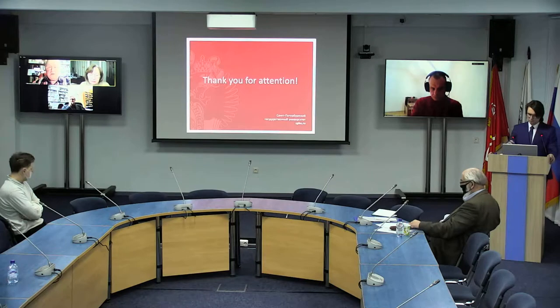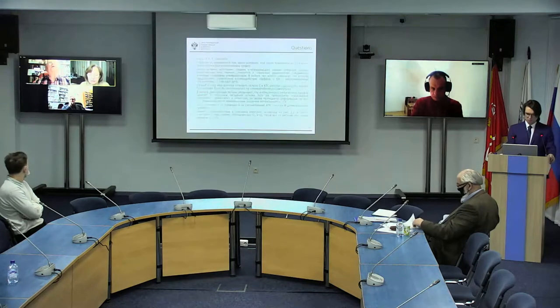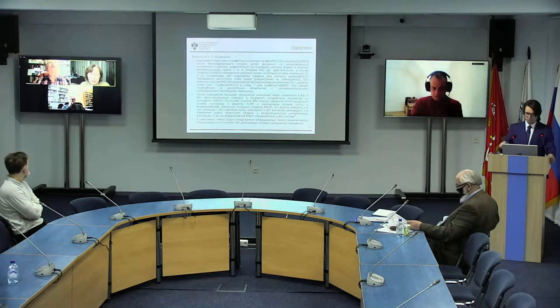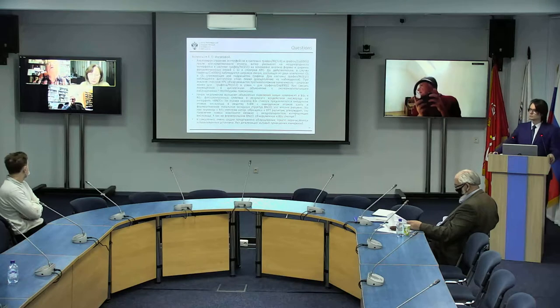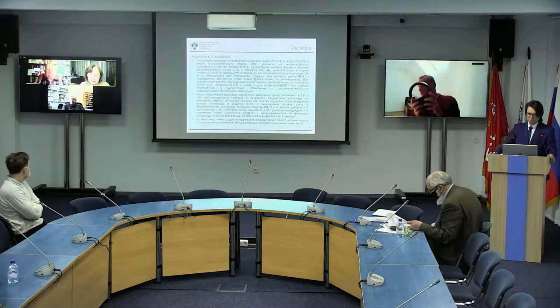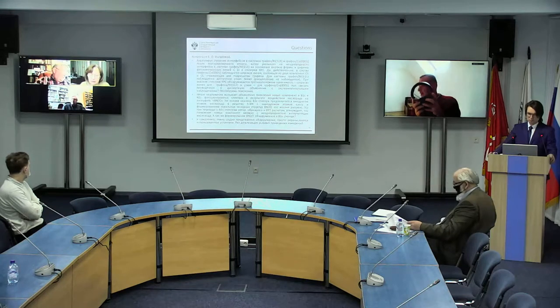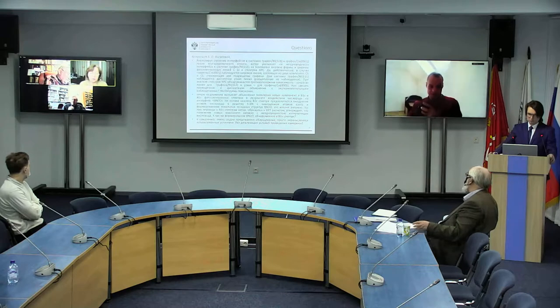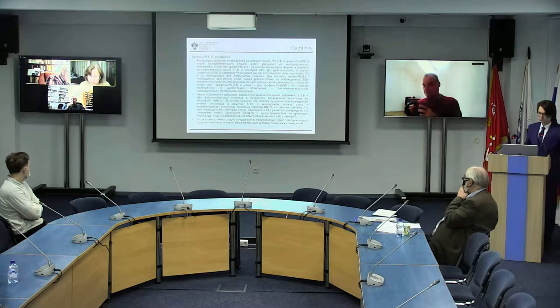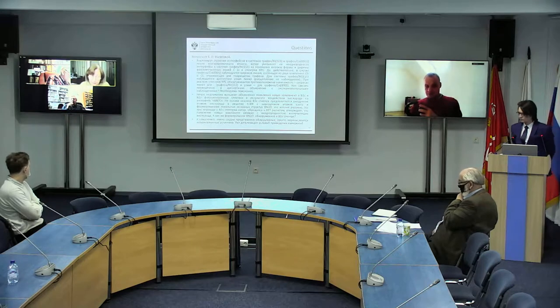First comment: analyzing the structure of interfaces in the systems graphene-nickel and graphene-cobalt after short-term annealing, the author mentions the heterogeneity of the interface in the graphene-nickel system based on the analysis of the form and width of photoelectron C 1s lines and the Raman spectrum.